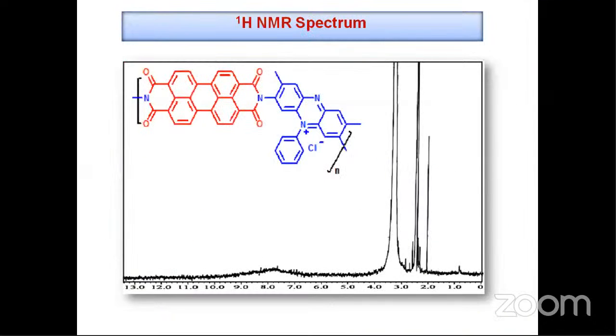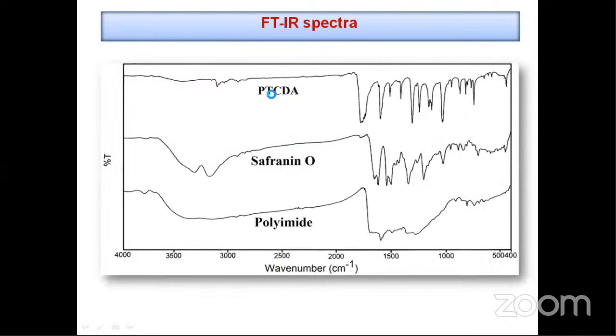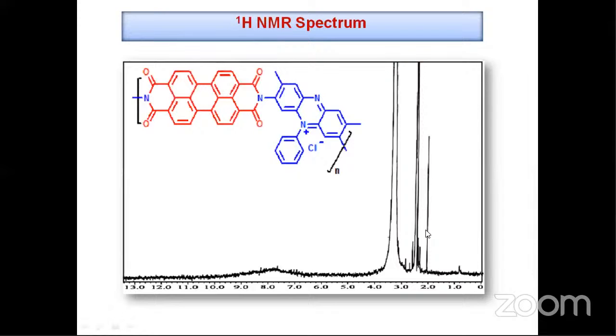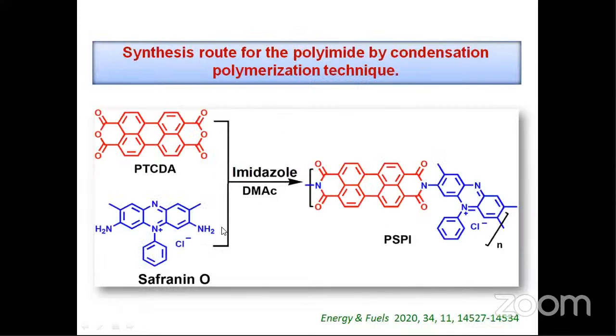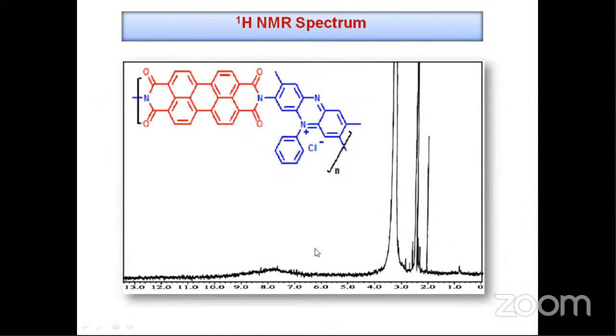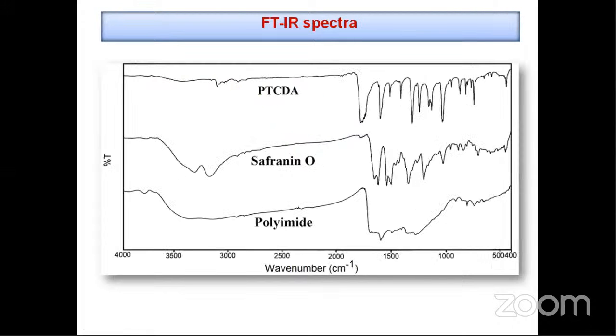This is the 1H NMR spectrum of the synthesized polyimide. In the 1H NMR spectrum, a broad peak was observed in the range of 7 to 9 ppm, which corresponds to the aromatic proton signal of the perylene dye and safranine O moiety. Here, the peak that appeared at around 2 ppm corresponds to the methyl proton of the safranine O group. Here, the disappearance of the terminal amino group of the safranine O moiety indicates the formation of the polymer with complete conversion of the monomers.